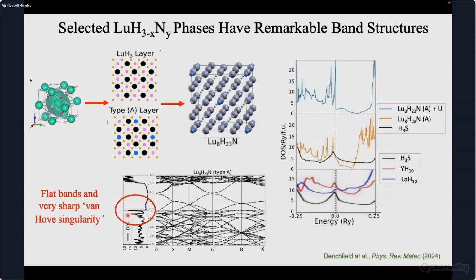And what you find is that with the appropriate ordering schemes, where you have all the nitrogens in this doped structure in the octahedral sites, you can produce a very sharp Van Hove singularity at the Fermi level. And I show here on the right that it's really quite sharp. It's much sharper than what we have when we do the same kinds of calculations for the superhydrides of yttrium and lanthanum, or for H3S. So there's a very interesting band structure in this material, apart from the superconductivity, but this is consistent with the superconductivity. And that's shown here.